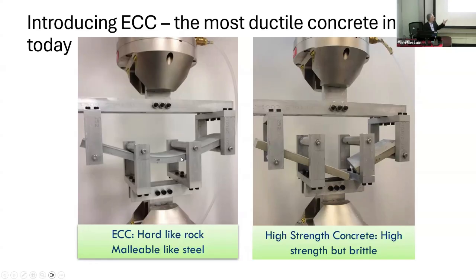But in ECC, you actually allow the material to undergo plastic deformation. I put it in quotes because it's not actually like steel plasticity, but it is damage tolerant. If you look very carefully on the underside of this slab here, there are micro cracks on the bottom. So the material is damaged, but despite the damage, the composite remains load carrying. It doesn't give up, okay?